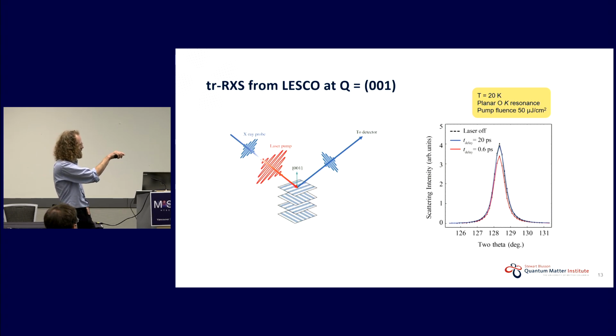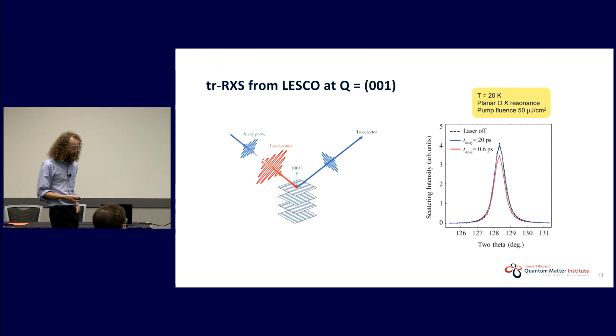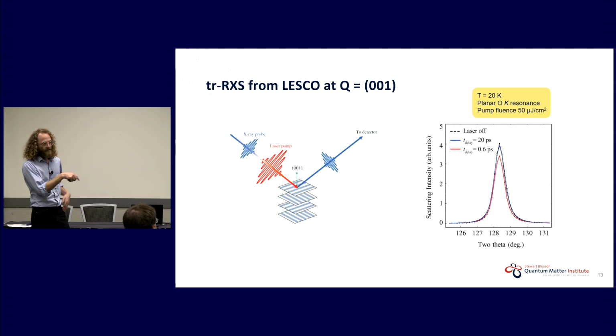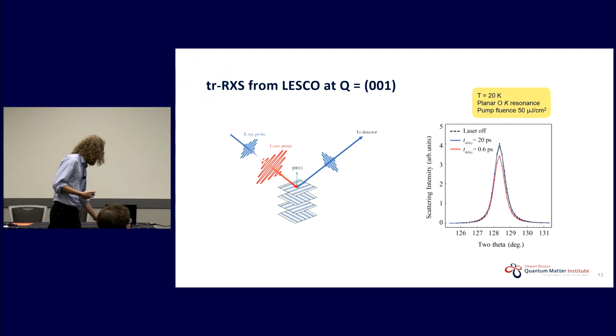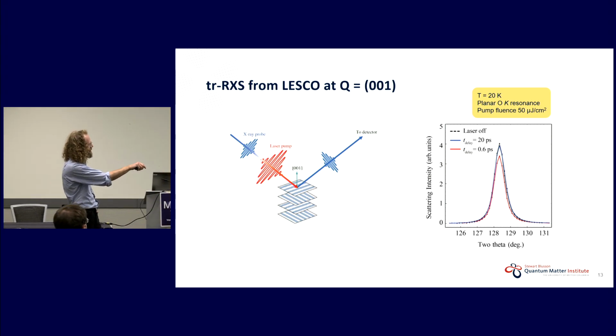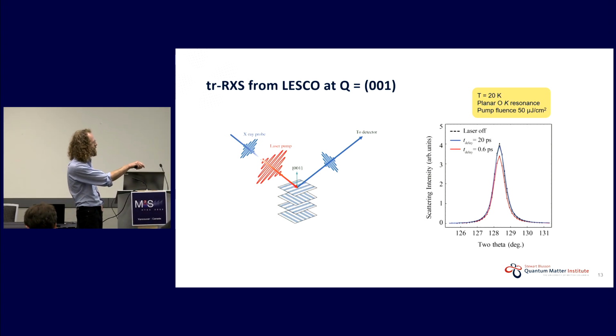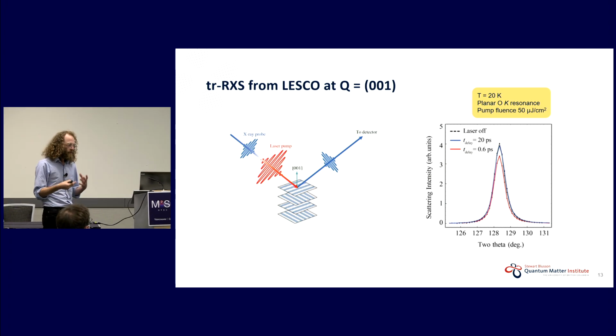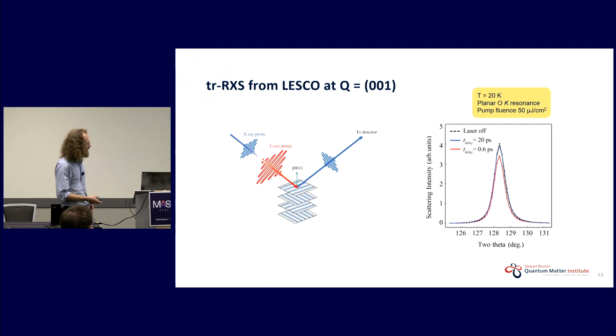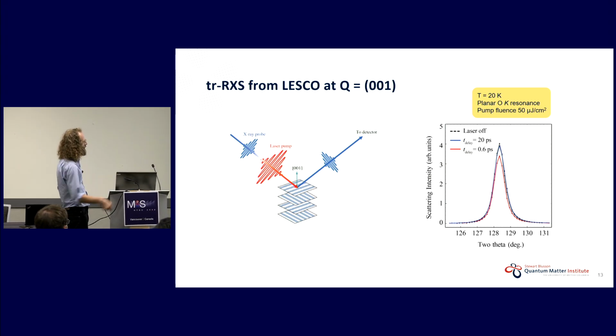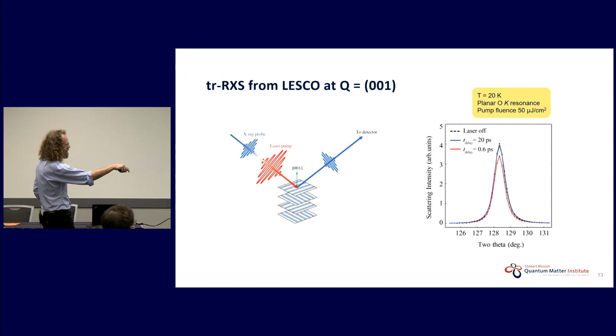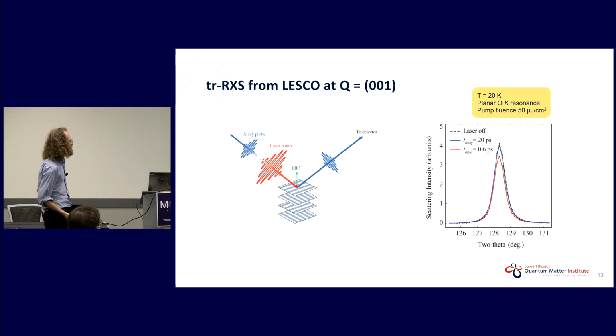And this is what the signal looks like. So the first thing to notice is that compared to the CDW reflection, this thing is much more intense. So it allows us a lot more sensitivity, let's say. And this is just to show you what the order of magnitude of the signal is that we are looking at. So here, the dotted line that you can hardly see is the equilibrium 001 peak. The red curve is sort of the maximum suppression in a fluence regime, which is the one we're going to operate in, so around 50 microjoule per centimeter squared. And then the blue curve, which looks sort of the same as the laser off curve, is after 20 picoseconds, so it's almost fully recovered.